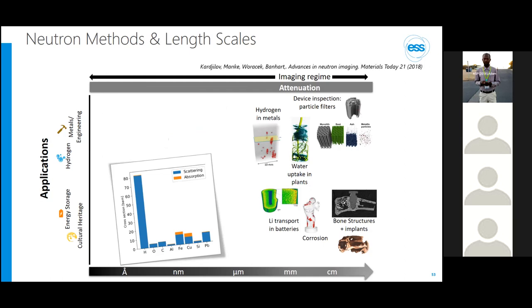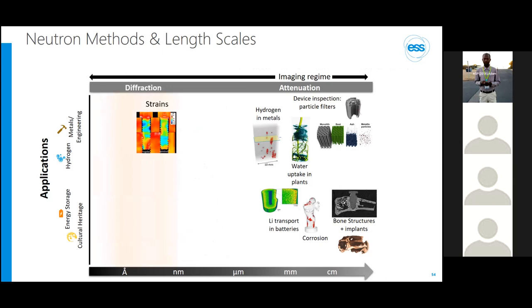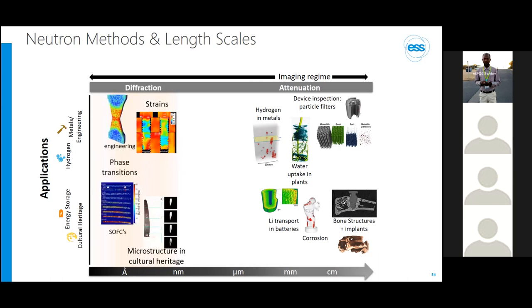In this regard, it's worth highlighting that the neutron imaging community has really succeeded in past years in exploiting these scattering mechanisms for advanced imaging methods, essentially expanding the imaging regime towards domains that were so far addressed by scattering techniques only. That allows us, for example, to exploit diffraction contrast to obtain images of strain distributions in metals. What you see here are some fasteners in two plates. Or to obtain local information about crystalline structures in Viking swords, for example. And one can follow phase transitions, for example, in metallic alloys or in energy devices such as